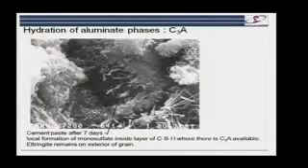Here, this is a kind of shell. This is like the shells of CSH we saw before. And inside the shell, you probably still had some aluminate phase. And because you have that aluminate phase there, that's why you form the monosulfate. Whereas outside, where it was a little bit isolated, these ettringite needles can persist essentially indefinitely.